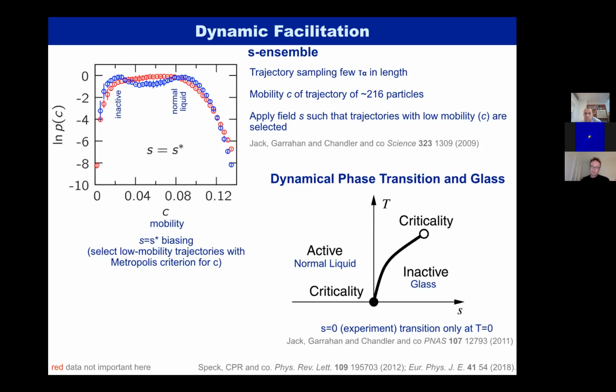Now, of course, we cannot sample at zero temperature because the system moves too slowly. And so everything at low temperature is speculation. There's no evidence for it, you can't measure it. So it is tempting to extrapolate this line to finite temperature, and that is what I'm going to focus on now. Everything in this gray region is speculation because the temperature is too low to run simulations or do experiments. In fact, we could simply extrapolate the line, and then this dynamical phase transition of dynamic facilitation would occur at finite temperature.